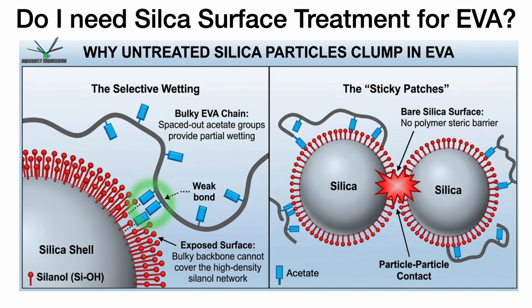The acetate groups, which like to interact with hydroxyl OH groups, are spaced out along the EVA backbone. This gives only partial coverage, in that not all of the OH surface groups will have an acetate group to interact with. The places on the silica surfaces that don't have an acetate group will be free to get close to a neighboring particle and stick to this neighboring particle since the OH groups like each other so much. The particle-to-particle contact will lead to clumps, which isn't good for color dispersion.